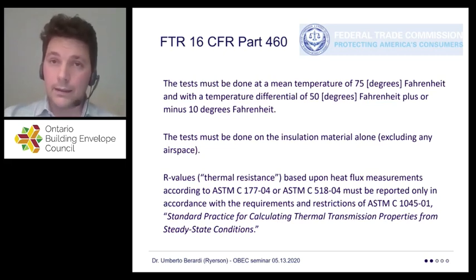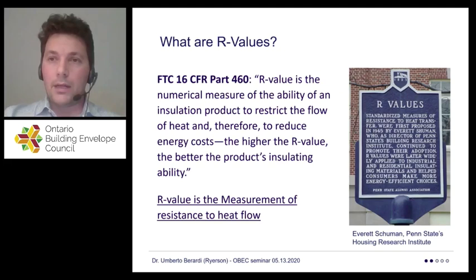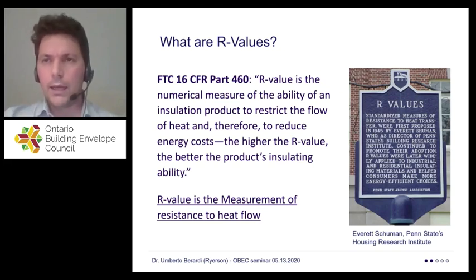There are other standards that are using different temperatures, but for now, let's focus on these numbers. These are the numbers that have been used, and if you want to do a conversion, you realize that testing a material between 50 and 100 Fahrenheit means testing a material with an average temperature of almost 24 Celsius, actually 23.8 Celsius.